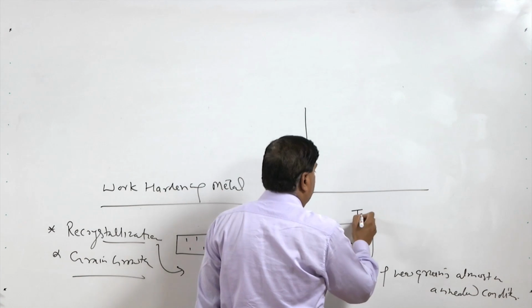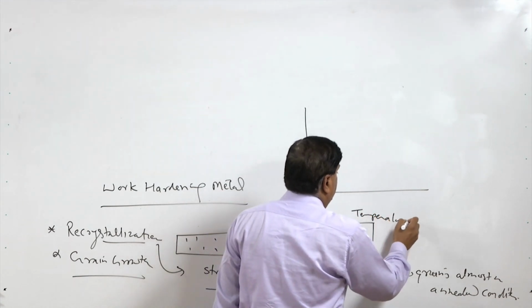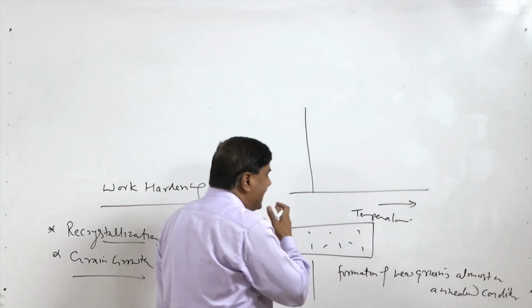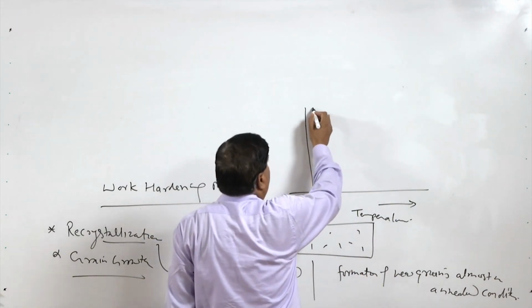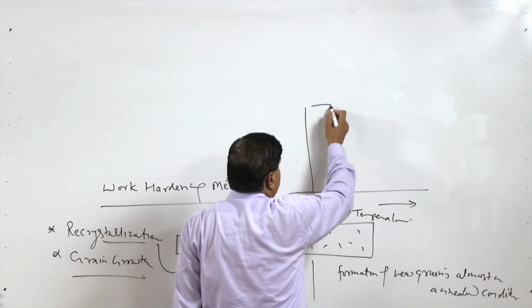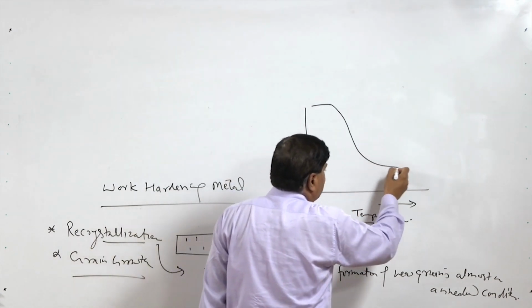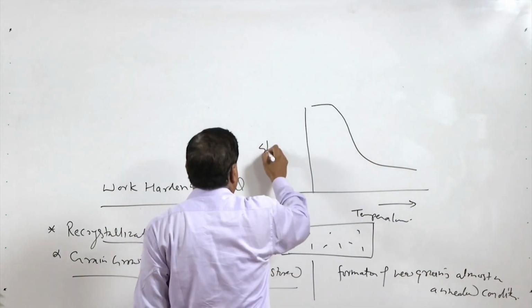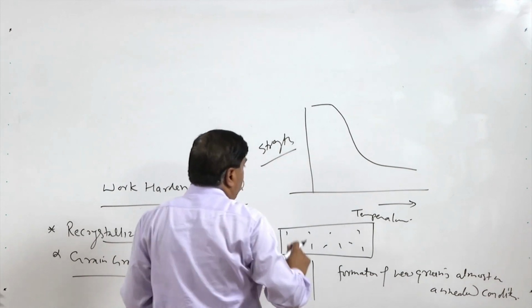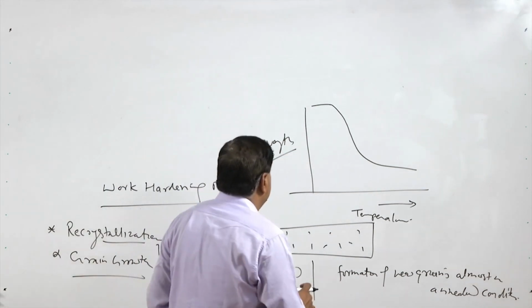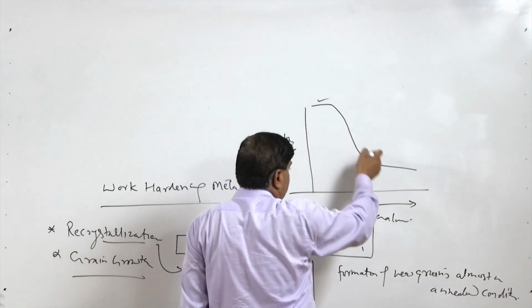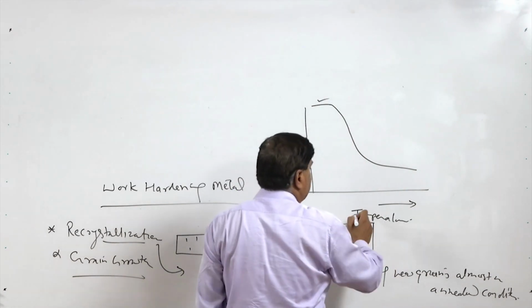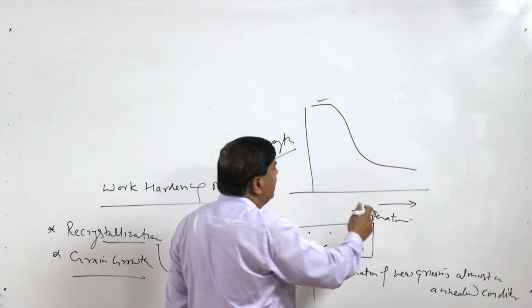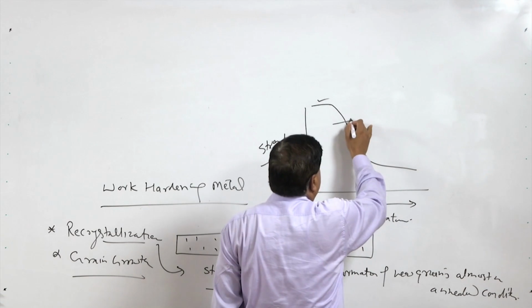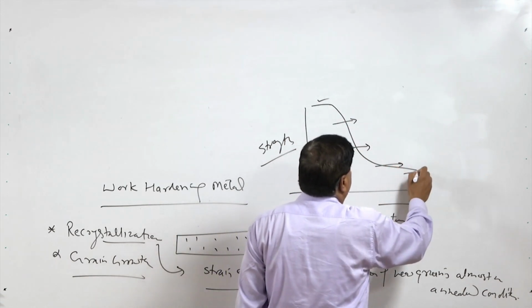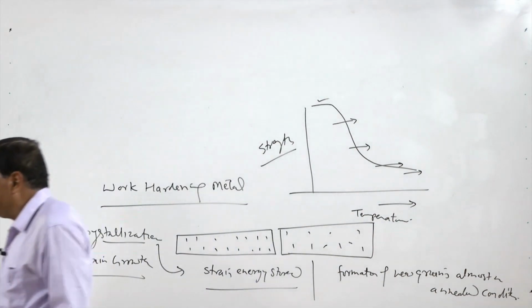Say the temperature of exposure: as the temperature of exposure increases, the metal which is in work hardened condition offers higher strength, and as the temperature of exposure is increased, we will see a significant reduction in the strength of the metal system. So, this is the strength of, say, cold worked metal, which offers very high strength as it is exposed at different temperatures. With increasing temperature of exposure or increasing annealing temperature, the extent of recrystallization increases and it lowers the strength of the metal system.